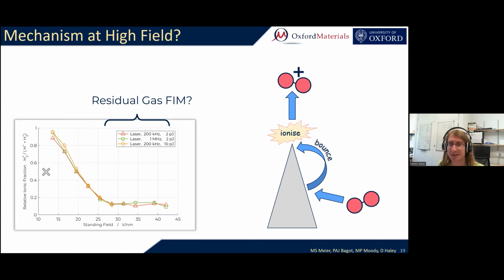The way it would work is this. We have a contaminant hydrogen in the gas atmosphere. It's getting attracted to the tip, polarized by the electric field, and attracted by the electric field. It's eventually bouncing around a bit, and then it's finally ionizing and flying into the detector. Now, the ionization in field ion microscopy is commonly believed to occur through a tunneling effect away from the surface. And this ionization away from the surface could possibly explain why we're seeing an energy deficit in there.